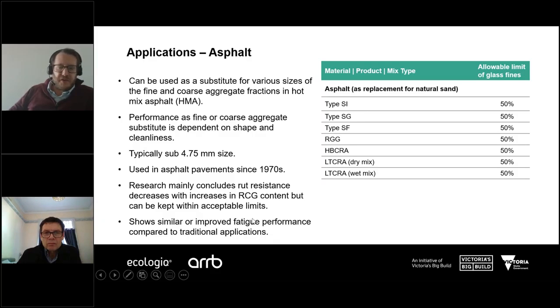Another concern for asphalt is the potential for stripping or moisture damage. Some of those concerns are related to the cleanliness of the glass, and the cleaner the glass, the better the adhesion of the glass to the bitumen, which prevents moisture damage.